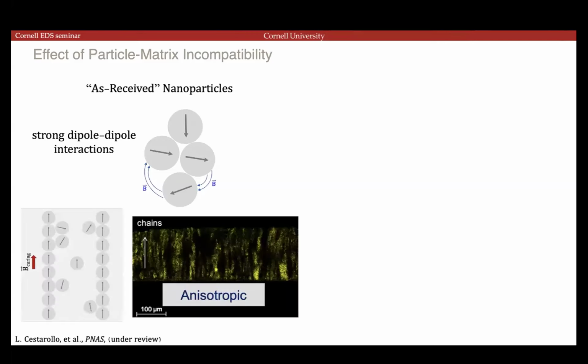The particles that we're using are iron nanoparticles that have no surface coating. So once mixed into the material, they're interacting very closely with their nearest neighbor, and that strong dipole interaction reduces the net magnetization. If these want to align anti-parallel so that the flux can go from one to the other one, then the net magnetization in this direction would be effectively zero. So if you mix that into the film and you still have these agglomerations, then in the end, that moment that I was saying is going to improve our actuation is now reduced.